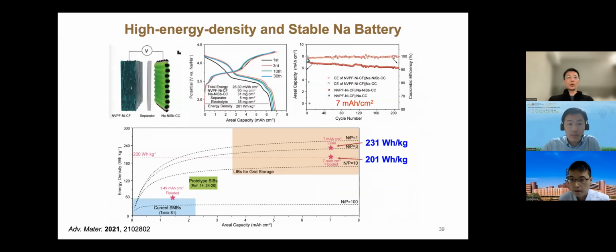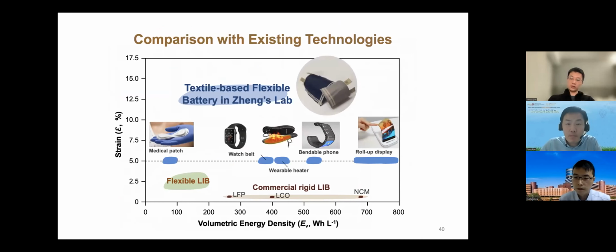So in this sense, we can use a very stable anode and then pair with a very thick cathode. The cathode is 7 milliampere-hour per centimeter squared. So we can build a very, very high energy cell. And this cell, if you calculate it with everything, is over 200 watt-hour per kilogram. If we use less electrolyte, a lean electrolyte, and of course we sacrifice the cycling stability a little bit, we can reach about 230 watt-hour per kilogram. And we believe this is one of the very best data when we published a paper that actually does overcome this 200 watt-hour per kilogram kind of threshold. Okay, so this is what we have right now.